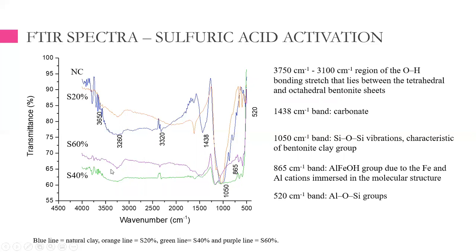There is also a change in the intensity in this band that you have here. And in the activated clays, you see that there is a decrease in this band, and this is related to the carbonates loss. And of course, this is due to the acid attack.